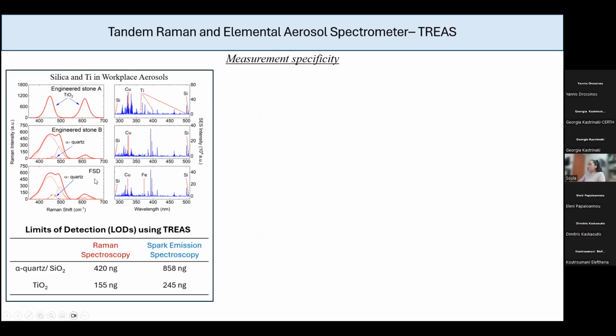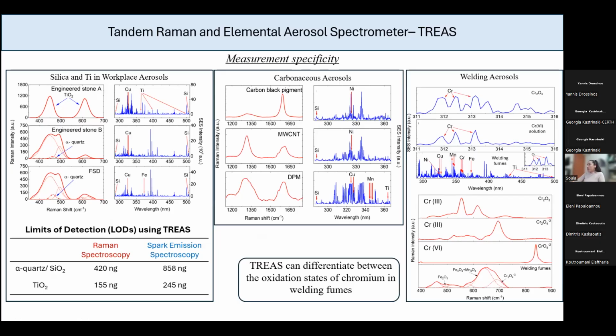And then in the fracking sand dust, is it again the same situation? We can see after peak deconvolution the alpha quartz peak. In either case, we could see titanium dioxide, either engineered stone B or fracking sand dust. Below, we see the limit of detections that were calculated for alpha quartz and titanium dioxide using either Raman or spark-emission spectroscopy. And here are some other applications where both techniques are required.